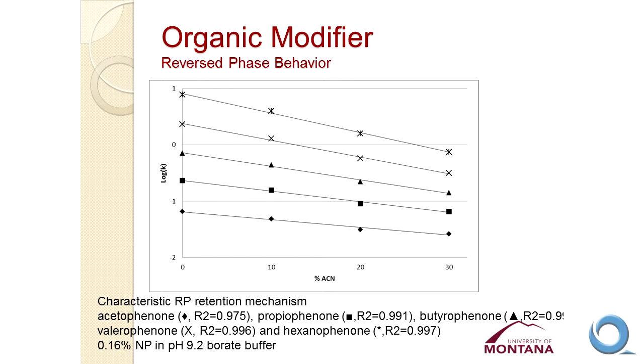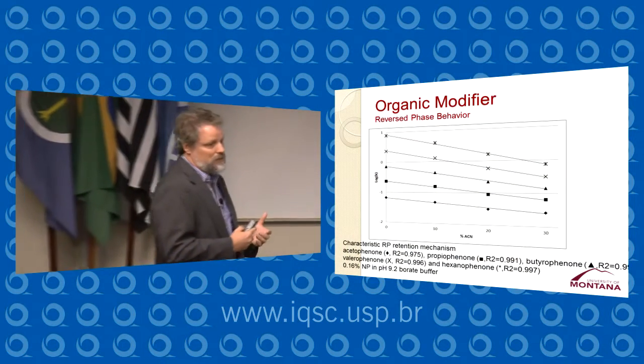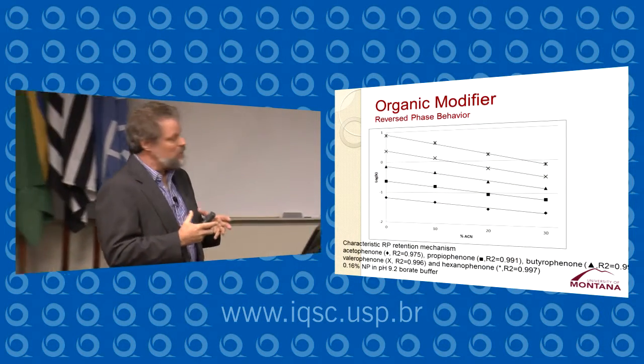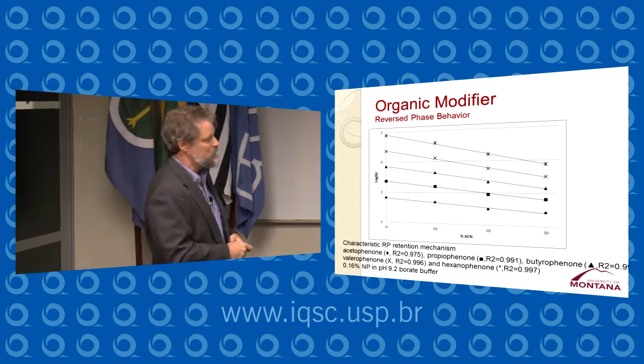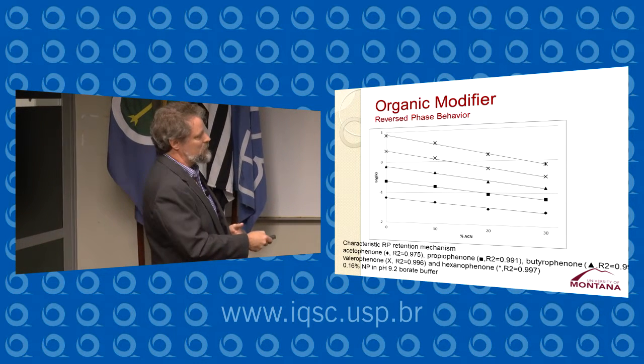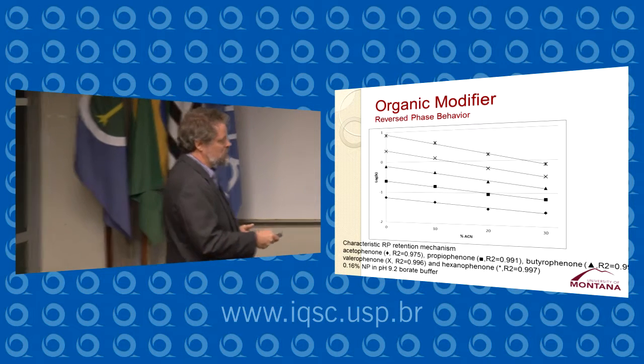The nice thing about that is that it allows us to predict what to expect in terms of retention as we change the organic modifier concentration. But the other thing that this tells us is that these nanoparticles are stable in these organic modified buffers. If they were falling apart, we would see some dramatic change in retention at some point.